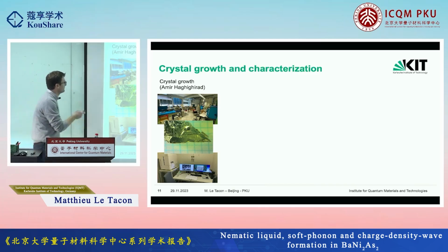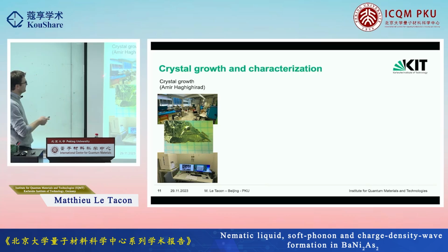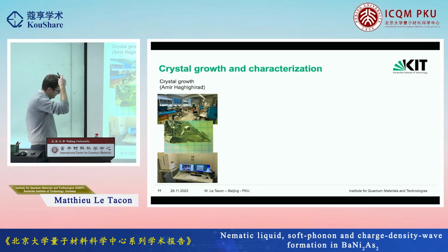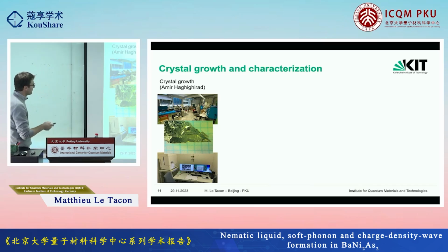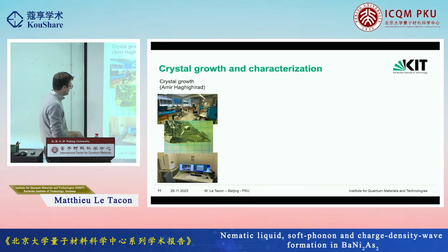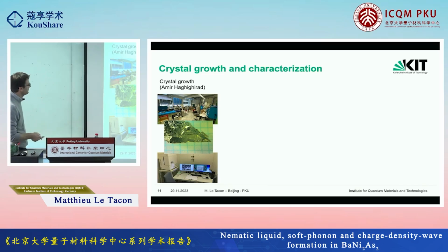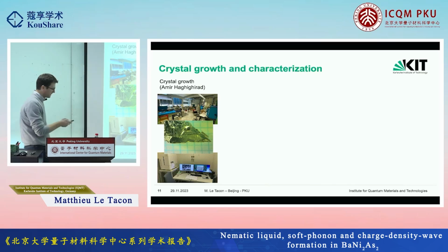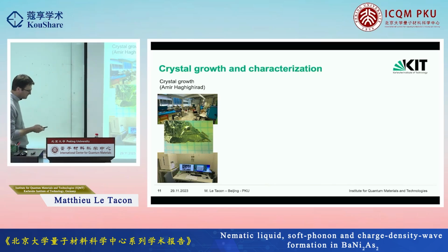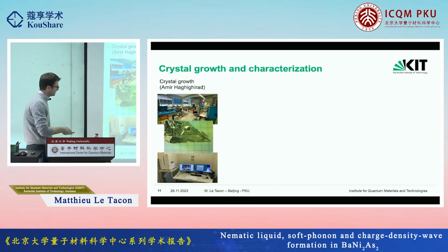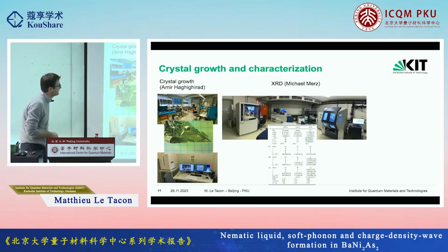At the institute, we have a solid crystal growth department. We have over 20 furnaces, actually even more now, where we can grow very nice and high quality single crystals that we can also analyze with a very handsome, small and versatile electron microscope to do EDX and check that the composition is fine.